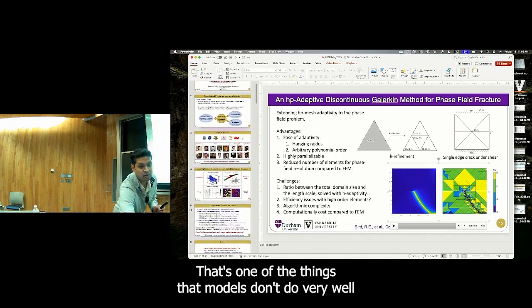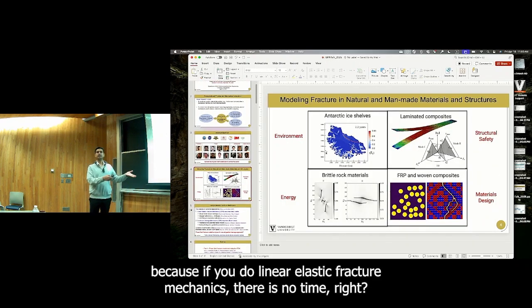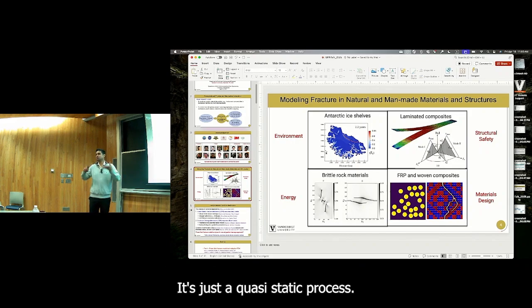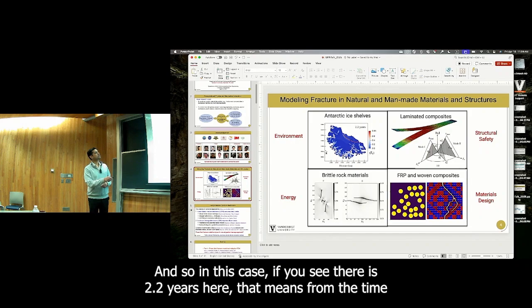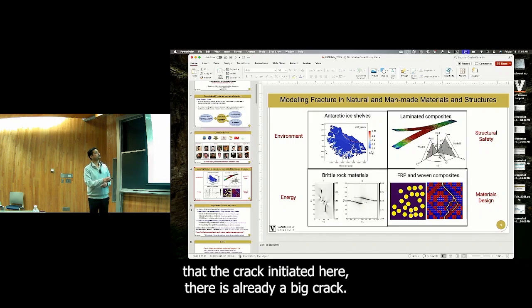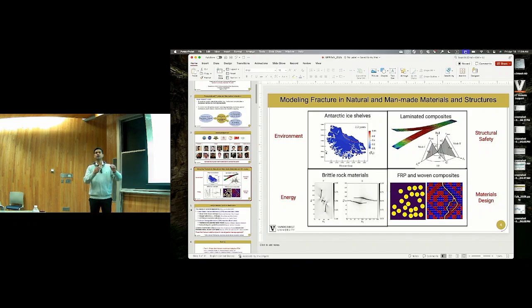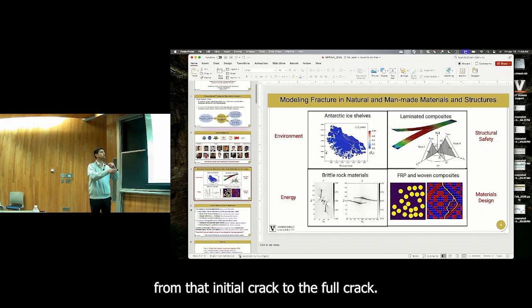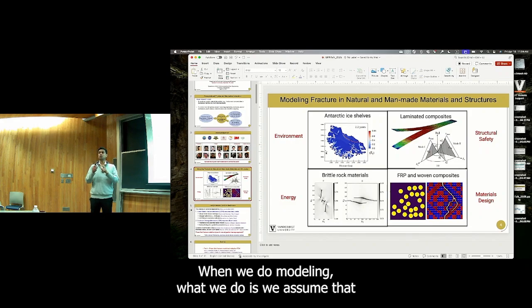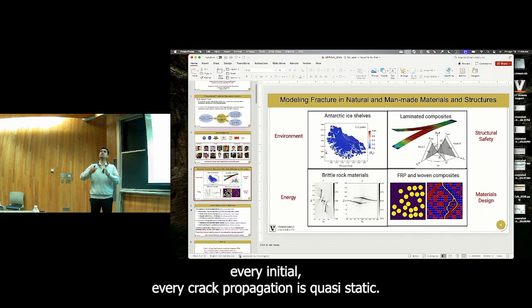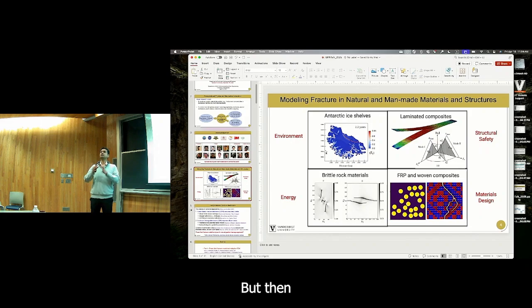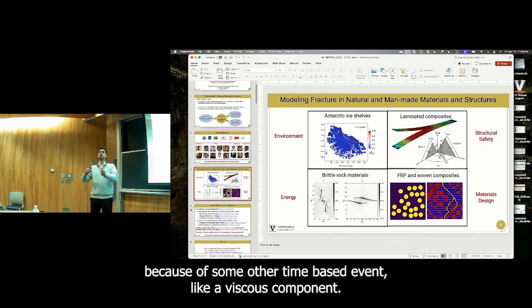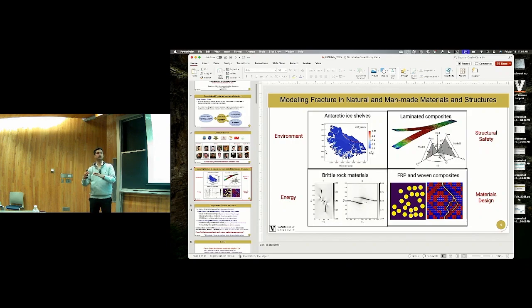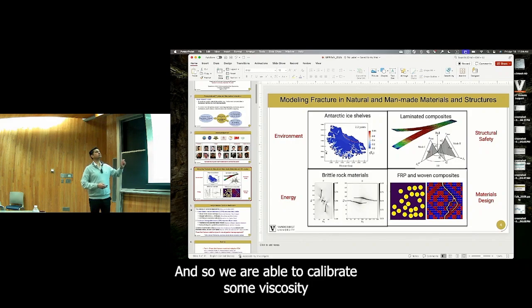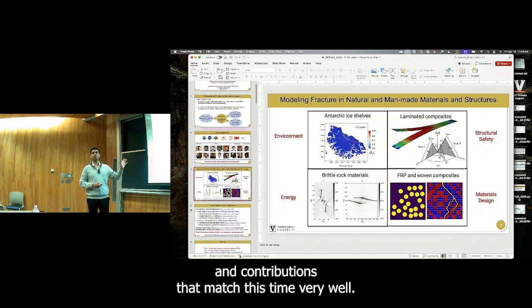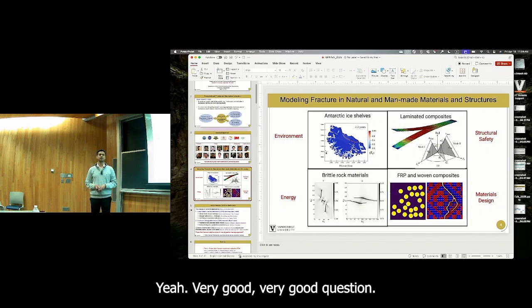That's one of the things that models don't do very well, because if you do linear elastic fracture mechanics, there is no time, right? It's just a quasi-static process. And so in this case, if you see, there is 2.2 years here. That means from the time that the crack initiated here, there's already a big crack, but then it took 2 years to go from that initial crack to the full crack. When we do modeling, what we do is we assume that every crack propagation is quasi-static, but then the driving force is changing because of some other time-based event, like a viscous component. And so we are able to calibrate some viscosity and contributions that match this time very well. But it's still calibration. We are not able to predict time. Yeah, very good question. Thank you.